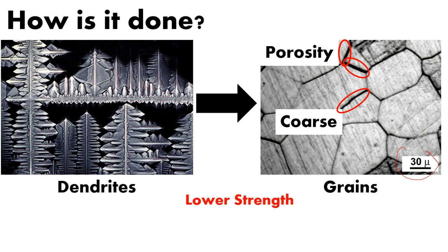Larger grains mean lower strength, it's more brittle, and it's much more prone to fatigue failure, due to the porosity. So if you have a design and you use steel that was made just straight from a casting, even though it's not guaranteed, it's much more prone to a fatigue failure, meaning if you load it and unload it, different types of cyclic loading, you're much more likely to have a fatigue failure due to these issues that you have because of the grains that the metal is made up of. So the very structure of the metal, the grains that it's made up of, actually determines the mechanical properties that you're going to get in the final metal.